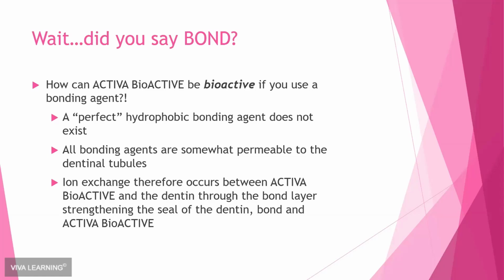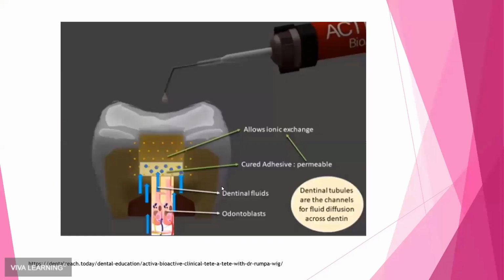We know that bonding agents are still somewhat permeable to the dentinal tubules and the fluid that passes through. So what ends up happening is that the ion exchange between the Activa Bioactive and the dentin actually is going to occur through that bond layer, and it's going to help to strengthen the seal. The way I picture it is that it acts like glue almost. So here's just a graphic of that. You can see here we've got the dentin. Dentinal fluid is flowing through the tubules, our adhesive layer, and then when we're placing the Activa, the ion exchange is still occurring through that layer of bond.